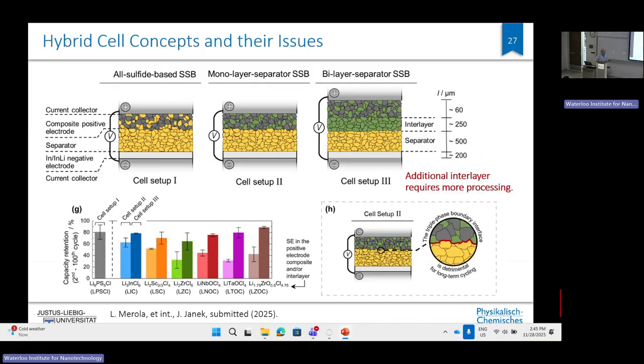And at the end, by systematic studies, they found out indeed that this is the benchmark cell, and what you see as capacity retention, take this simply, these bars here, simply as a measure of stability of these cells. So this is for this cell concept rather stable. And these here, the dark colors, always are for the different materials. The higher bars, the more stable ones, are always this cell concept where one interlayer more is shown here, and where we avoid, in principle, triple phase boundaries between two different electrolytes and the cathode material. So clearly, this triple phase boundary has to be avoided. And going deeper into that, which I will not do, there is lots of chemistry going on at these triple phase boundaries. So the two electrolytes via the cathode material react, and that is the reason why this simple cell concept, which looks so nice, does in this case not operate so well, and we always need some more interlayer, and then in principle you can achieve a higher stability.